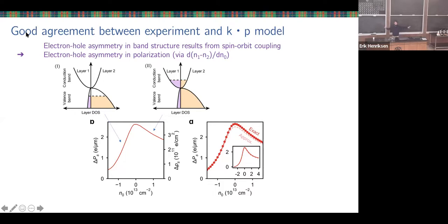So if you start with no polarization and you have a very layer polarized thing, you start to fill it up. And so you get a very rapid rise in the polarization. Right? And so this is now a charge neutrality here. And now if you go to the electron bands, they're much more symmetric, right? Now you start to fill them up and some screening happens, but it doesn't entirely cancel out the layer polarization that is coming from the hole bands.